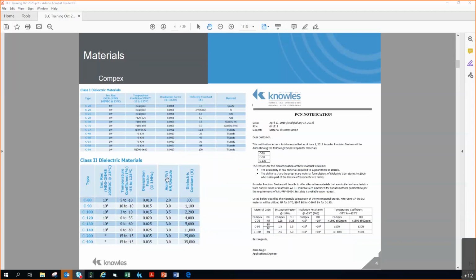Cherian, is it the back oxidation process that they do? Yes, it's controlled by the back oxidation process and the grain control. Okay. So it's very, very similar. We don't offer it. If someone wants that high K, it's typically for the telecom industry anyway. So that's typically what we see.